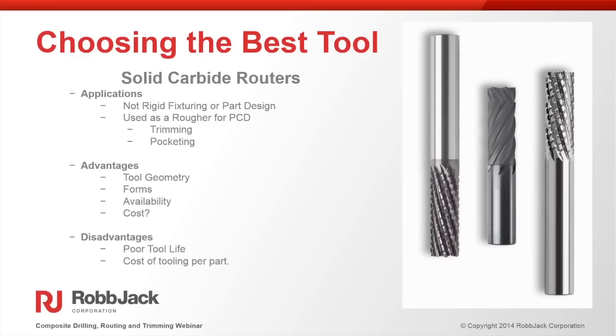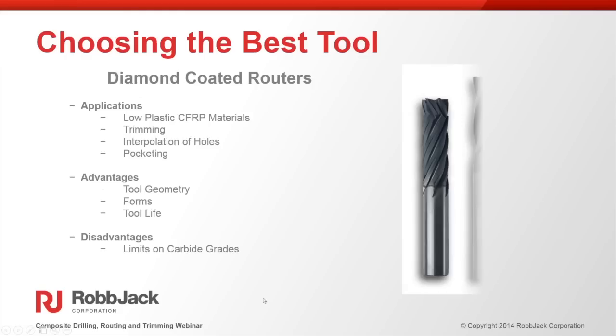Some of the advantages with carbide are unlimited tool geometries and forms, and a low cost. But the disadvantage is that it's an initial low cost, but high cost for production because you have such poor tool life with carbide in most composite materials. I've seen cases where just cutting 6 inches, the diameter of the tool is already 10,000ths smaller. So in a lot of cases, it doesn't work very well. You'll have a lot of uncut fibers and tearing of the surface when you only use carbide.